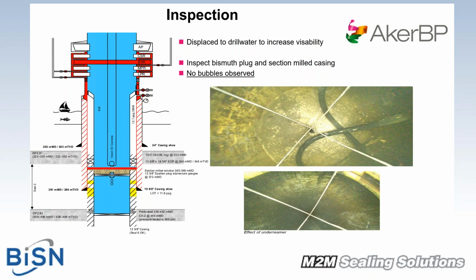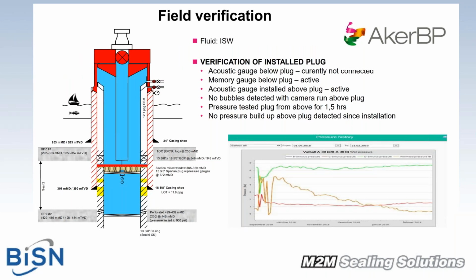Did it look like the test plugs that we'd set when we were doing the testing in our workshop? And it did. Apologies for the O-ring that was there, that fell off the BOP in the hour or so between setting the plug and the camera run, and the company never actually told Aker BP that they'd dropped that O-ring down the well, so it was a little bit surprised to see that on the camera shot. Since then, it's been on long-term pressure test continually for the last 15-16 months now.